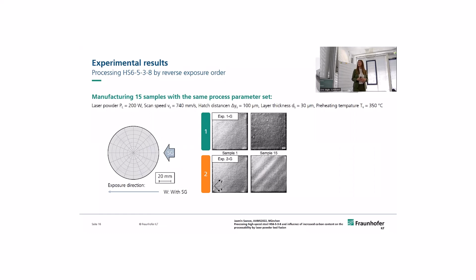And we even went a bit further and changed the exposure direction with the shielding gas flow, because previously you saw the standard exposure direction always against shielding gas flow to prevent interaction with byproducts. If you go in the exposure direction with the shielding gas flow, you force them maybe to interact a little bit. And if you look at it, you cannot see as much as before that there is an influence, but there's still a little bit uneven surface compared to the one with the setup 2.